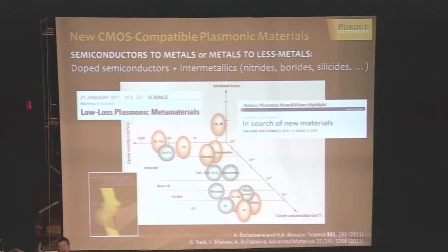If you have the electric permittivity for your plasmonic components at -100, whereas for the electric component it's say +2, it indicates that the thickness of your plasmonic component should be like 50 times smaller, which is impractical. If your electric component is 10 nanometers, you cannot make something that's just a few angstroms - it doesn't make sense.